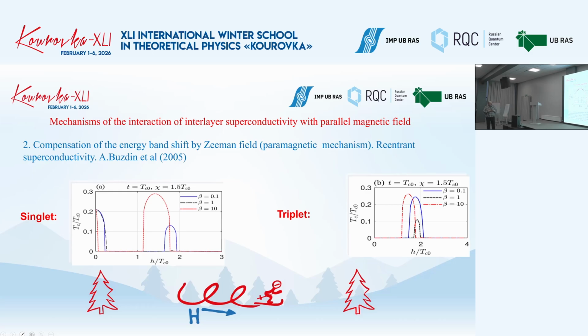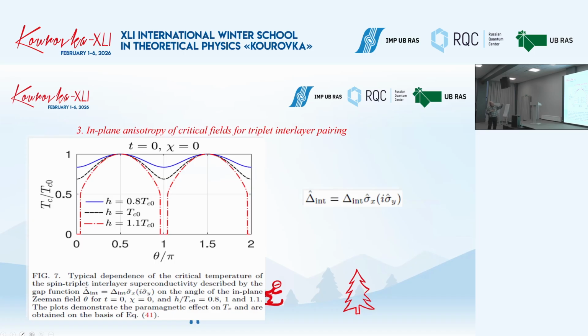And finally, if we include in our consideration the triplet pairing, this interlayer pairing, and also this spin splitting effect of the magnetic field, we can get this two-fold anisotropy as they observe in experiment. So this particular fact seems that it can be explained within this picture.